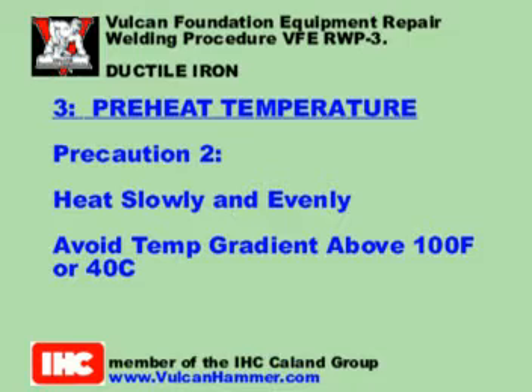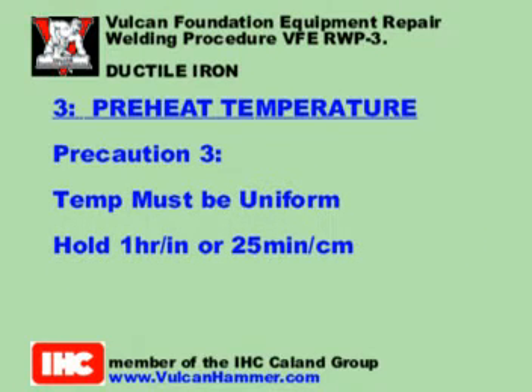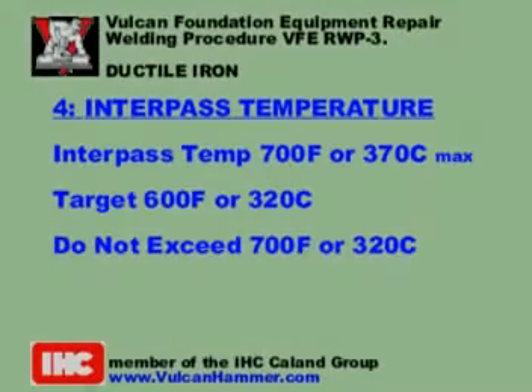Item 2. Heating must be done slowly and evenly. Temperature gradients of more than 100 Fahrenheit or 40 Celsius should be avoided. Item 3. The temperature must be uniform throughout the section preheated. Holding times of 1 hour per inch or 25 minutes per centimeter of metal section should be observed.